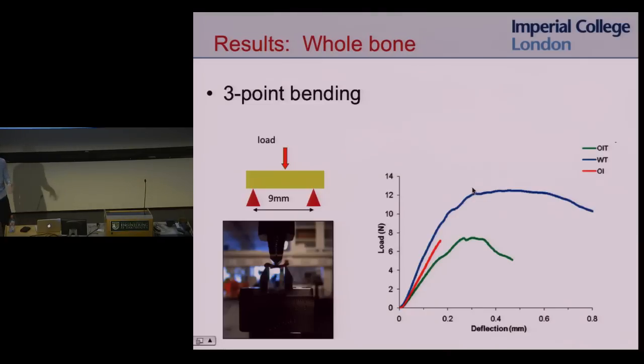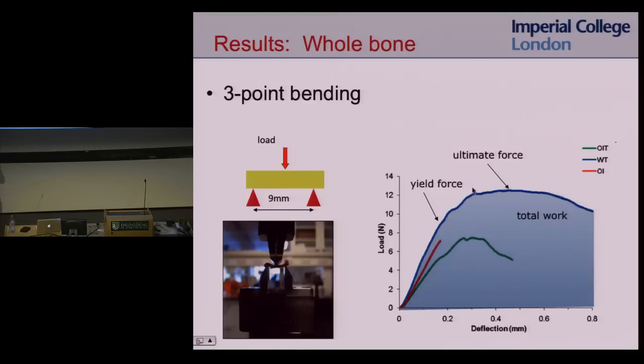The things you can measure from these load-deflection curves are the ultimate force, which is the maximum force the bone can take, the yield force, which is a transition from where it's linear to nonlinear, and the total work, which is the area under the curve, and this work can be divided into elastic work and plastic work. So if we take the ratio of the plastic work over the total work, that gives us an idea of how brittle it is. If it's very brittle, there's going to be no plastic work, such as this OI bone right here. And what we find is, as you can see from these representative curves, the stem cell treated bones